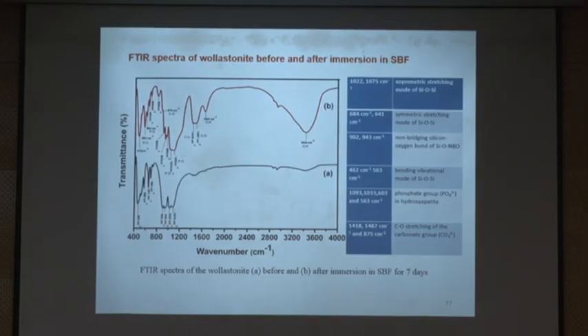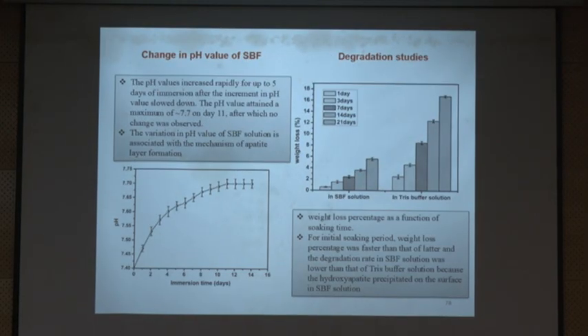So similarly, you can confirm by means of FTIR. You can confirm the activity even with pH also. See what is happening. We are preparing the SBF at 7.4, but it is increasing. So there is a change in the pH of the SBF because of the material. Even degradation, the weight loss, we can also calculate. So why is weight being lost? Because of the activity.